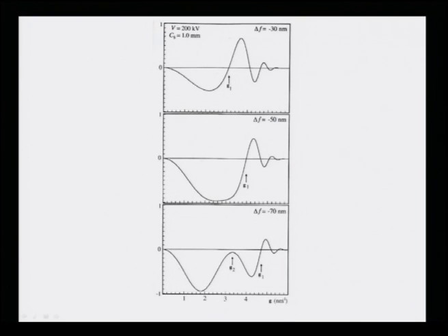and then we can look at what happens as a function of the defocus, as a function of delta f. So delta f is varied here for a 200 kilovolt microscope with CS 1 millimeter from minus 30 nanometers to minus 70 nanometers. As we vary from minus 30 to minus 70, the transfer function profile as a function of g is changing drastically. For a very low value of delta f, that is minus 30, the g1 comes at a frequency like this, and there are several zeros after this g1.